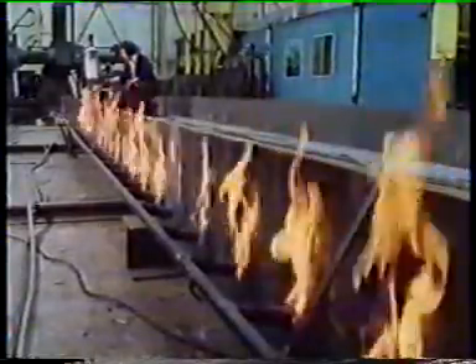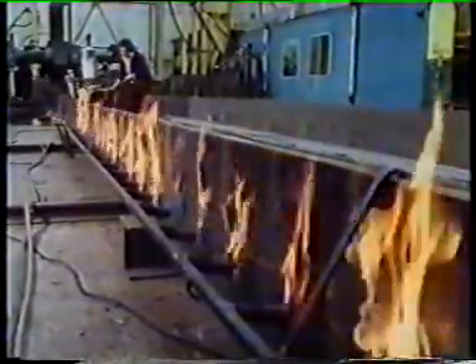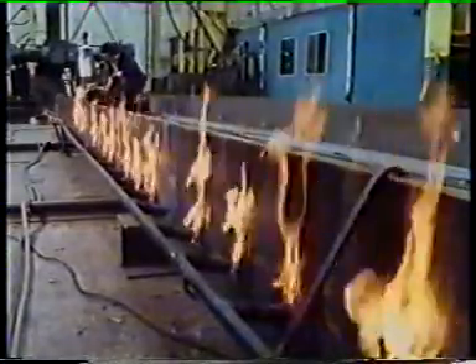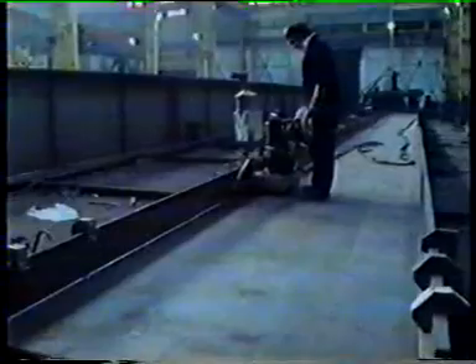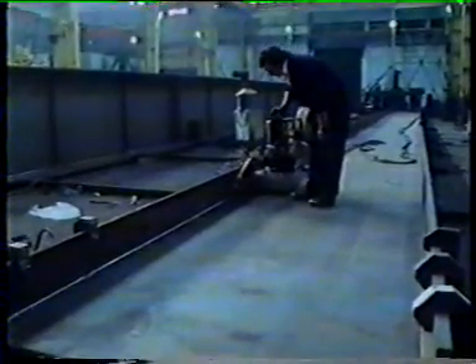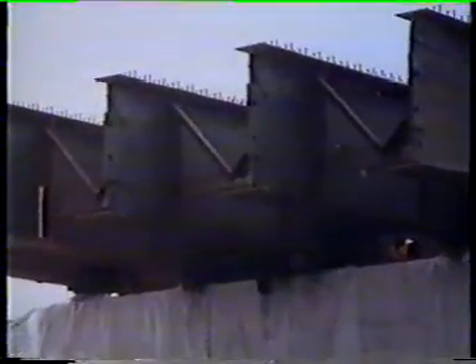This girder is being preheated so that the metal to be welded will have a uniform starting temperature. When the joint has cooled, the solidified flux is removed and the unused flux recycled, leaving a clean weld. The quality of the weld is excellent, and it needs to be. This girder will eventually become part of a bridge and will have to withstand 60 or 70 years of stress and strain.